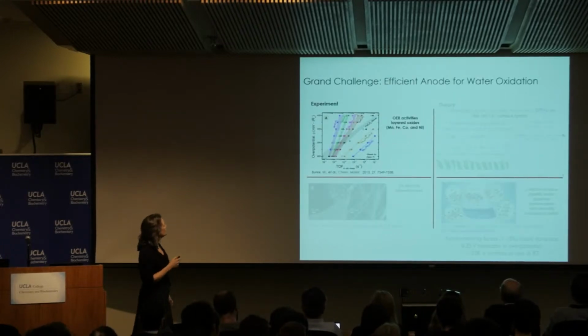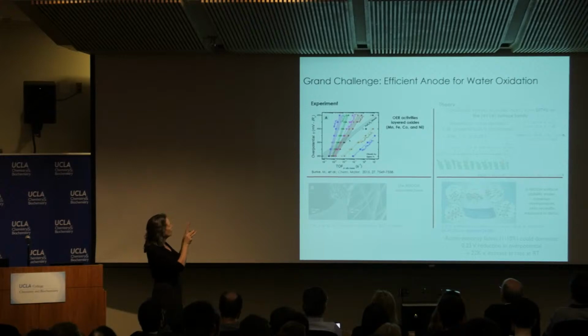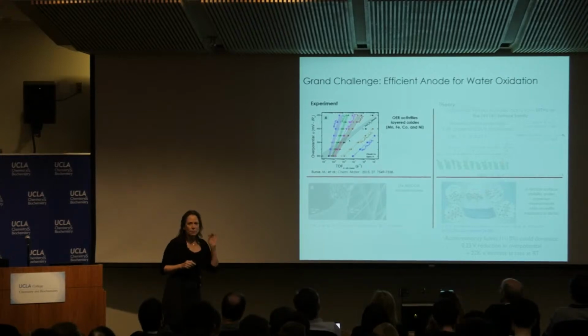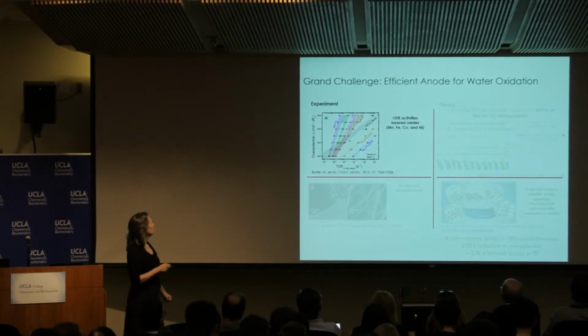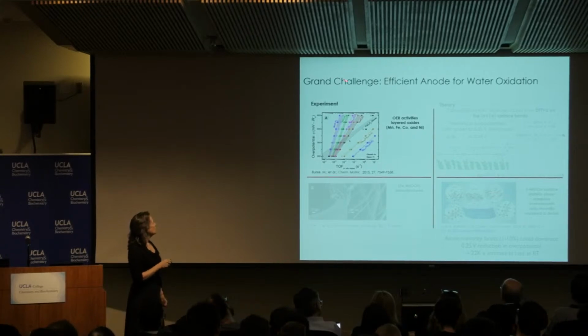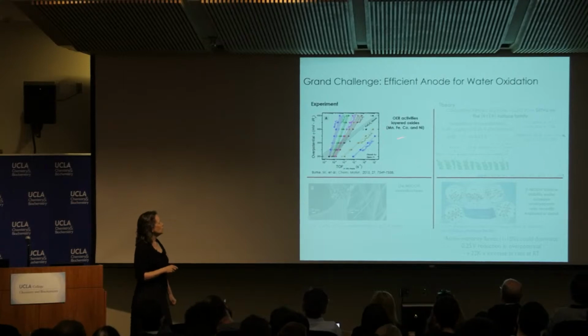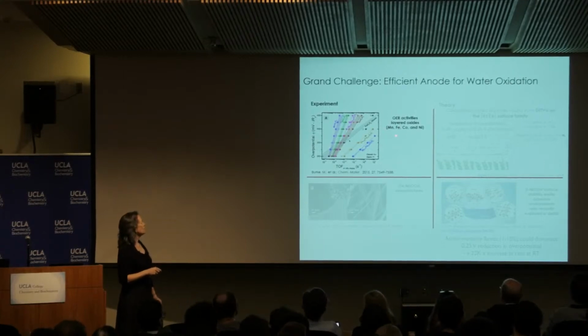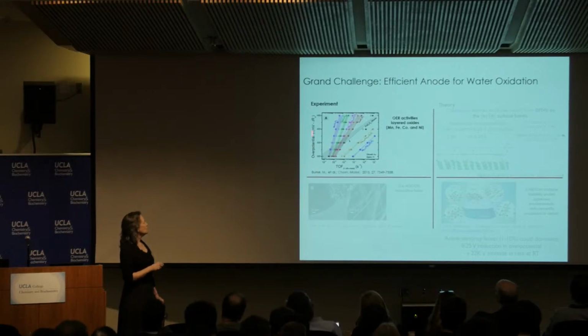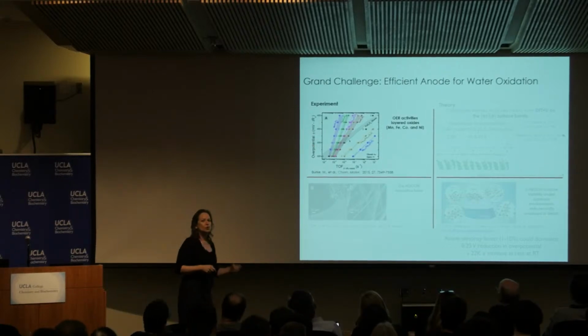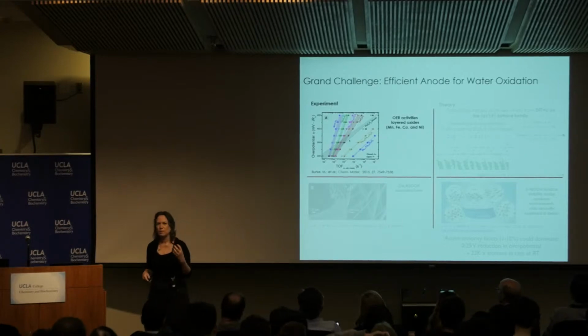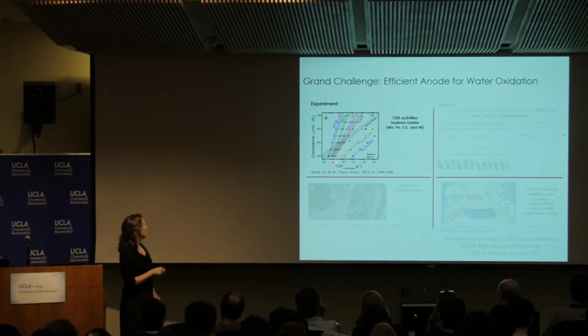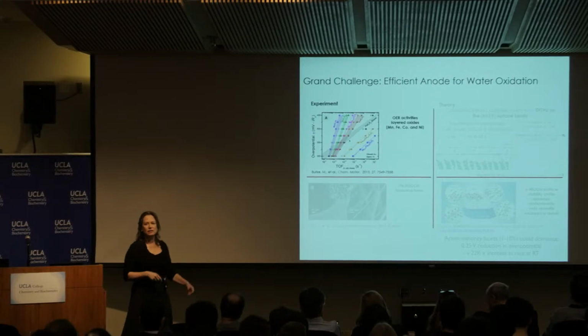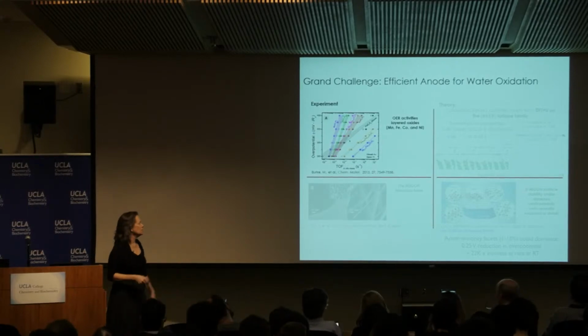Now I have one slide that shows essentially a summary of some experimental data to give you a sense of where we go from here. So this is a series of these metal oxyhydroxides with different first-row transition metals in the mix, either pure or mixed together. And what's being plotted here is the so-called overpotential, which you can think of as essentially the kinetic barrier. And then there's the catalytic turnover frequency, which is essentially the rate.